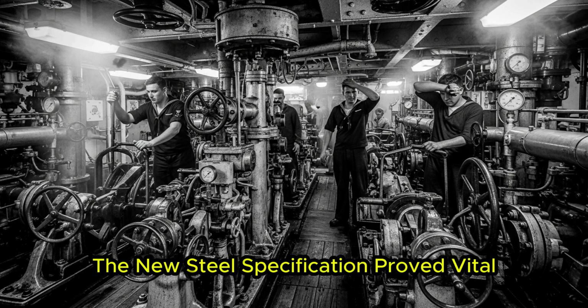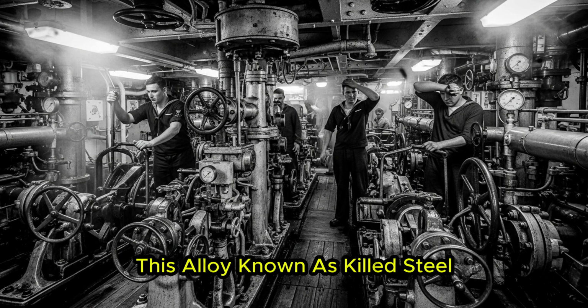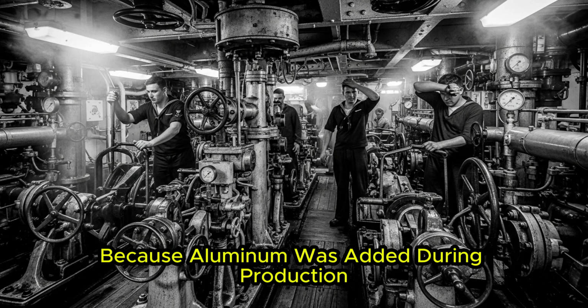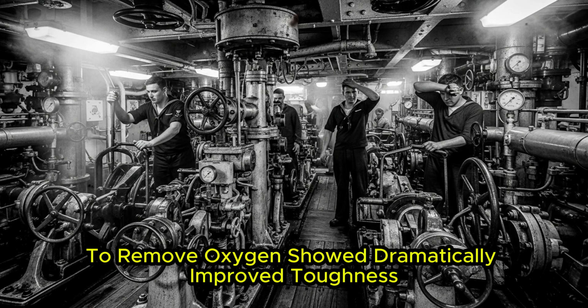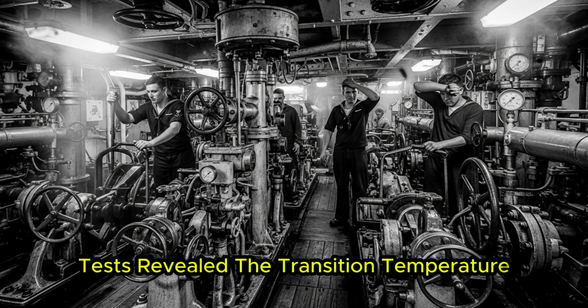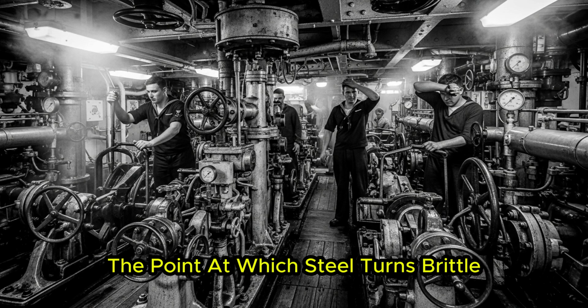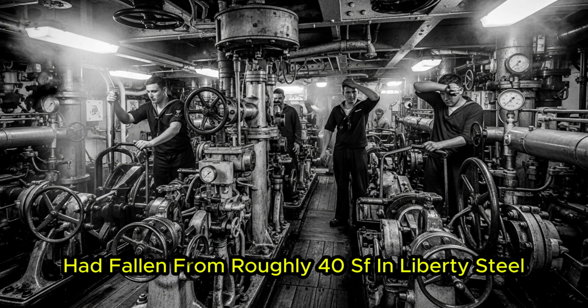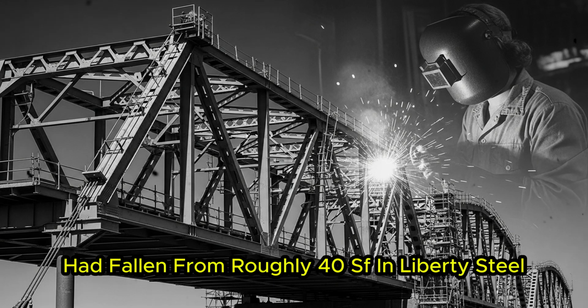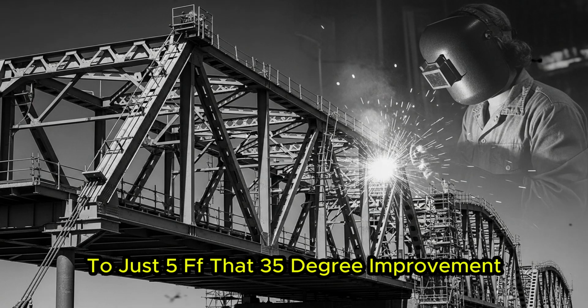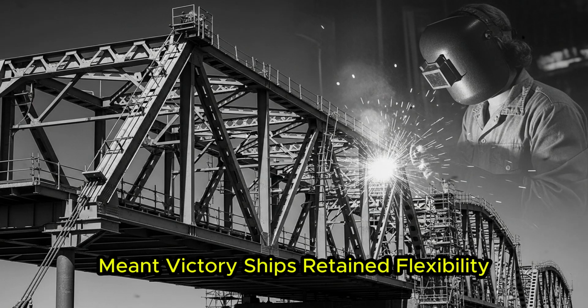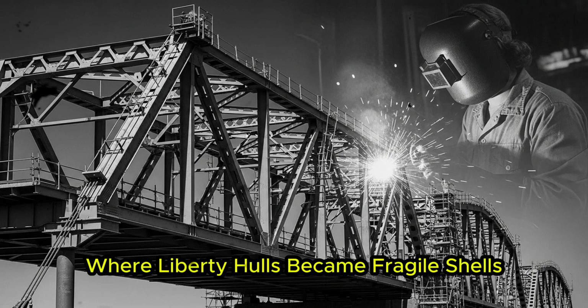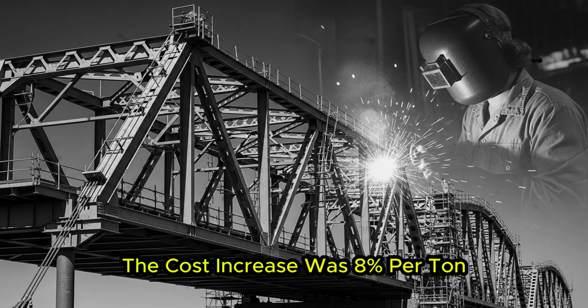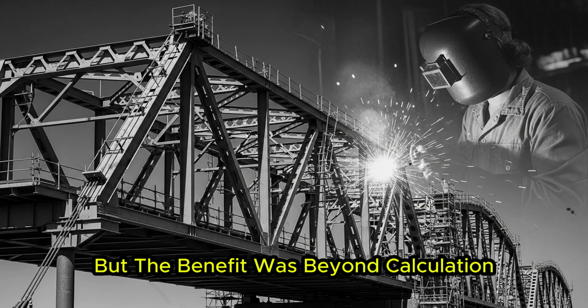The new steel specification proved vital. This alloy, known as killed steel because aluminum was added during production to remove oxygen, showed dramatically improved toughness at low temperatures. Tests revealed the transition temperature, the point at which steel turns brittle, had fallen from roughly 40°F in Liberty steel to just 5°F. That 35-degree improvement meant Victory ships retained flexibility, where Liberty hulls became fragile shells. The cost increase was 8% per ton, but the benefit was beyond calculation.